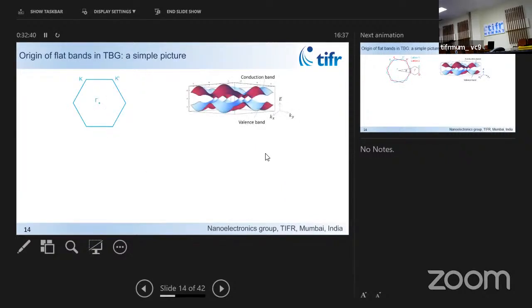So where does it come from? If I take a single layer of graphene, it has a band structure which looks like this. This is energy, this is momentum. Roughly this is of the order of electron volts, from the point where the bands meet. But most of the time when we do the physics, we do an expansion, or low energy effective Hamiltonian, around these high symmetry points. That is the essence of all of this exciting physics. The subtext, or fine print, in most of these experiments is that there is an energy interval over which this Hamiltonian is a valid description of the system.